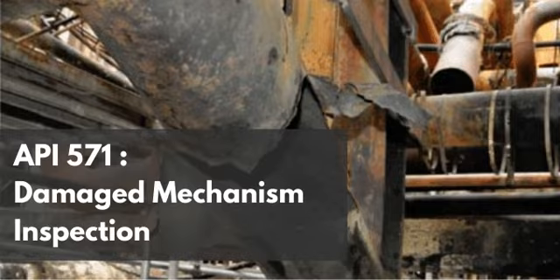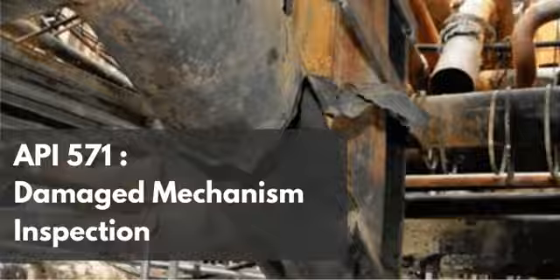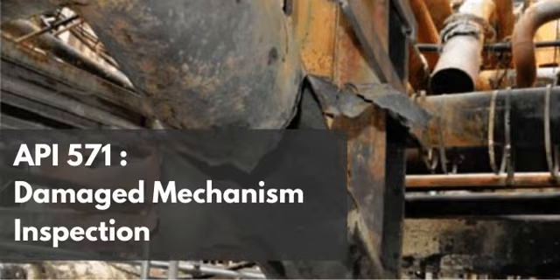So it is a brutal double-edged sword. You're gaining these brittle, glass-like carbide inclusions that ruin your mechanical strength, and simultaneously, you are losing your chemical shield, making the metal highly susceptible to other forms of attack. Exactly right. The data highlights the physical consequences of this microstructural degradation very clearly. It states that carburized steel becomes severely brittle, it may spall or crack, and it actively reduces and can completely eliminate the remaining sound metal wall thickness.